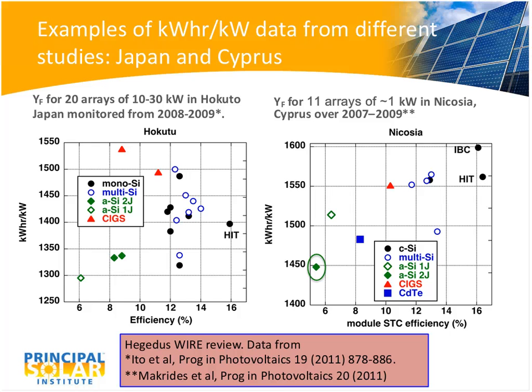And then over on the right is data from the group in Nicosia, Cyprus, over 2 years, showing similar technologies. Here you see that the HIT cells did quite a bit better, and the best was the IBC cell from SunPower. The CdTe module in blue, or array, should have been much better, again, based on its temperature coefficients and such, and yet you see it was sort of mid-range. So again, this is data telling us that what we'd expect doesn't always occur in reality. So people dug much deeper, and if you read their papers, you can find out some explanations for some of this discrepancy.